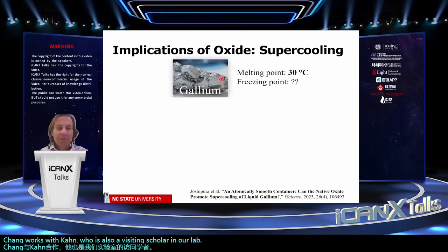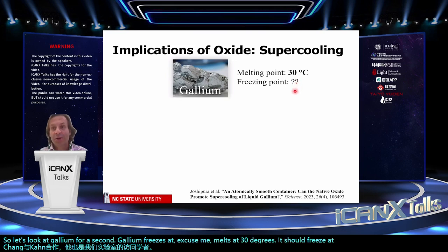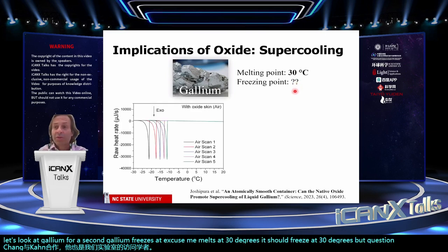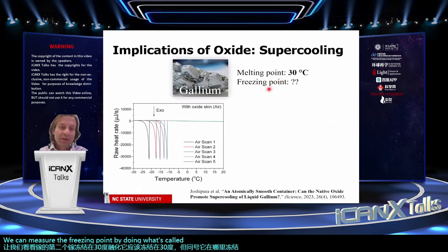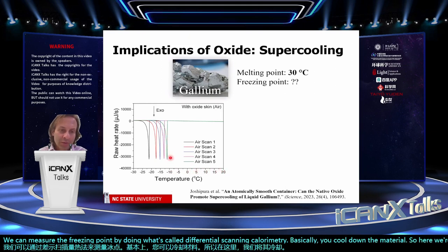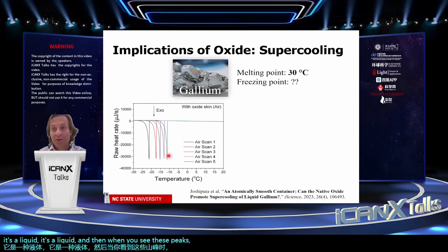So let's look at gallium for a second. Gallium melts at 30 degrees. It should freeze at 30 degrees, but where does it freeze? We can measure the freezing point by doing what's called differential scanning calorimetry. Basically, you cool down the material. So here we're cooling it down. It's a liquid, and when you see these peaks, that means you get a freezing event.